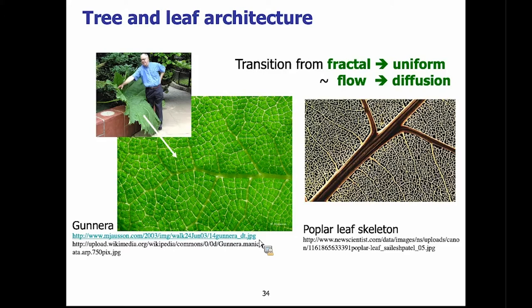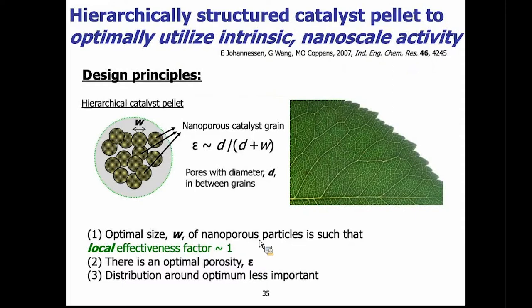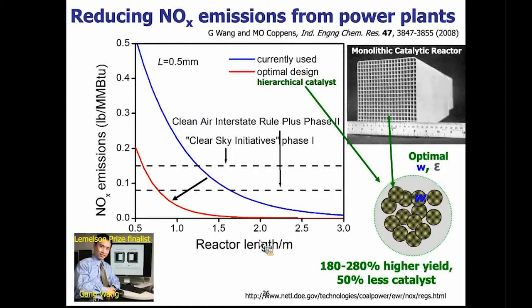Now, what's interesting is that when you look at the processes that are happening, this is completely in parallel with the physics. This is the fact that you change the transport from pressure-driven flow and capillary-driven flow to a diffusion-limited process. And so that's the idea that we used here. So when you then redesign these porous architectures of catalysts, you can form hierarchical catalysts where you find, by computationally assisted design, that indeed nature got it right, where you have these uniform particles with a size that's just like this, so that you maximize the efficiency within these small particles, say of a size W, and you have a porosity that just allows the molecules to access larger channels, small nanoparticles. Okay, so locally you have very high efficiency and you maximize the overall effectiveness, while the distribution around these pore sizes is not as important.